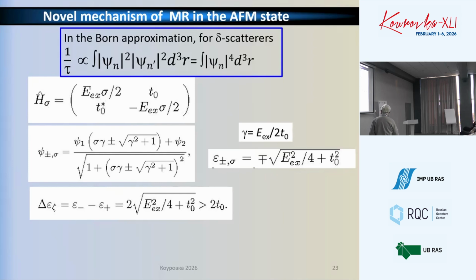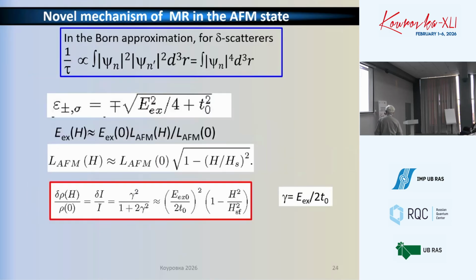And the splitting here will be a function of two parameters: the exchange splitting of the energy levels of the conduction electrons and the hopping amplitude across the layers. This one can be calculated, but the hopping amplitude can be estimated from experience because it's difficult to calculate across the layers. And this is the splitting which is responsible for the effect, as I will show further. Now, as I explained, the hopping amplitude across the layers doesn't depend on magnetic field, whereas exchange splitting does depend on magnetic field.